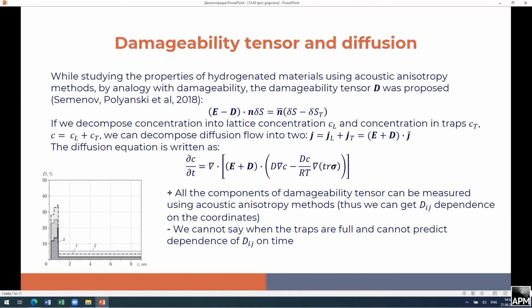The good thing of this approach is that all the components of this damageability tensor can be measured, so we can use experimental numbers. But the problem is that we cannot describe when these microvoids or microstructures will be full with hydrogen and will not work as traps. And also, we cannot predict this dependence on time. Otherwise, we should measure this damageability tensor every second, I would say. So we don't have any laws of how the damageability tensor depends on, for example, time or stress state yet.